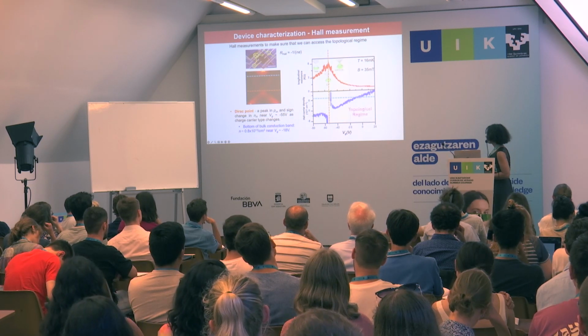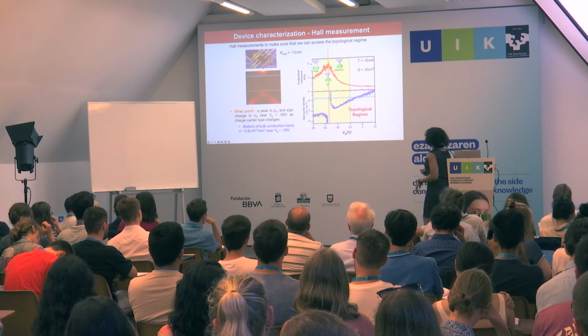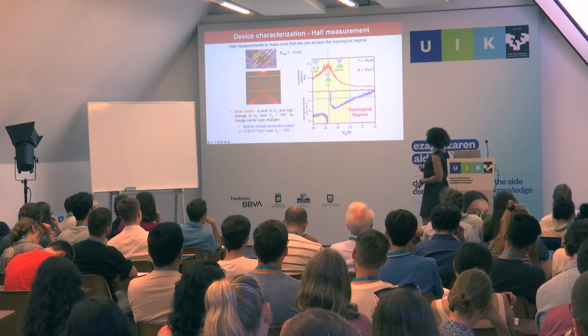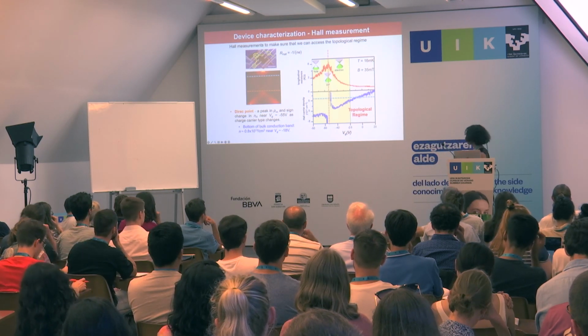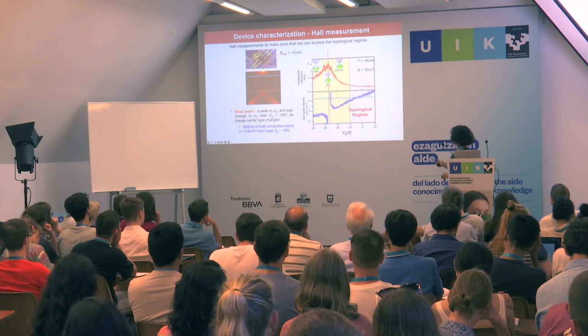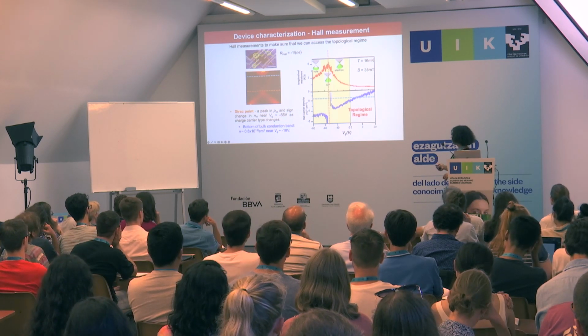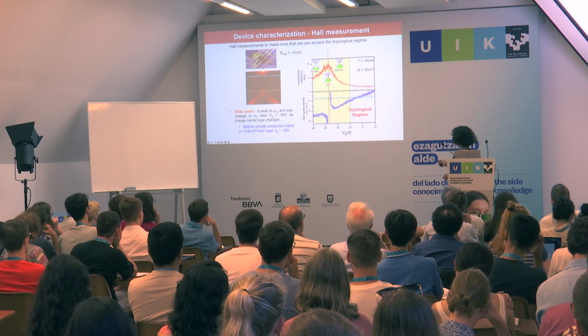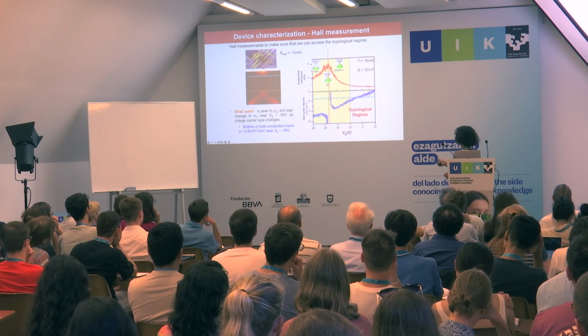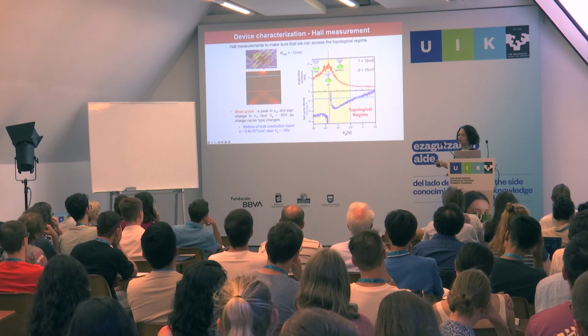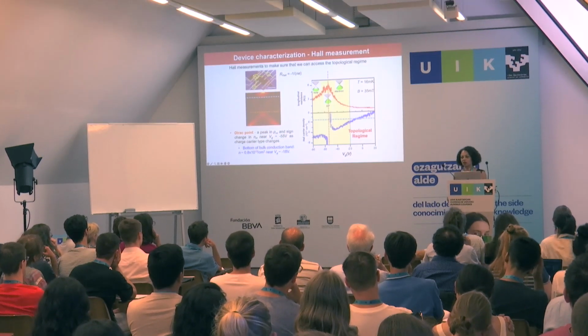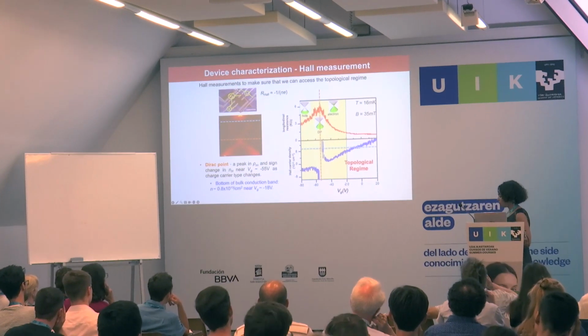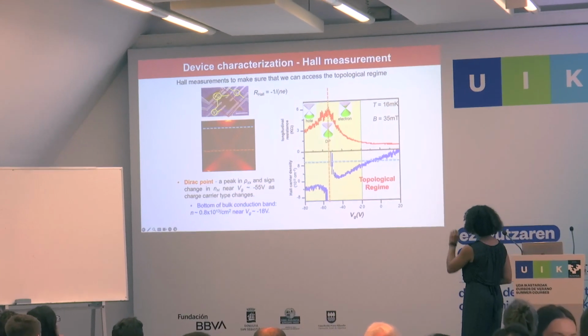Okay. So at least we can estimate where we are in the topological regime. And as was mentioned, we're comparing this to ARPES. So when I say we're exactly at 20 volts, you should consider this just a region. If we're out here somewhere, we're in the bulk region. If we're very close to around here, we're almost certainly in the topological region, without being really exact about it, which is hard to do without doing ARPES in situ for the doped system.